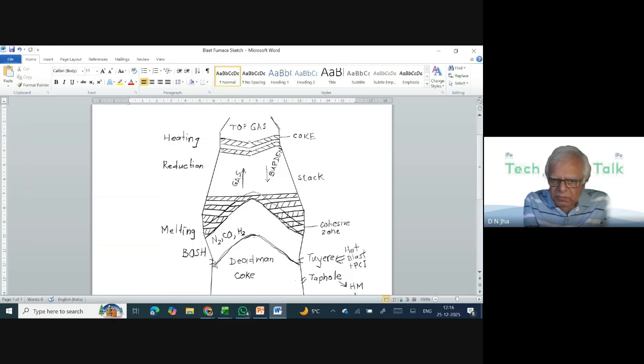Here, you can see the small thing that I'm showing you. This is the tuyere, and through the tuyere, we inject hot blast. Blast is basically air or enriched air at high pressure. It may have oxygen enrichment, it may have some amount of humidity. Plus, we also inject pulverized coal at this very level. That is also a source of carbon, like we said before.